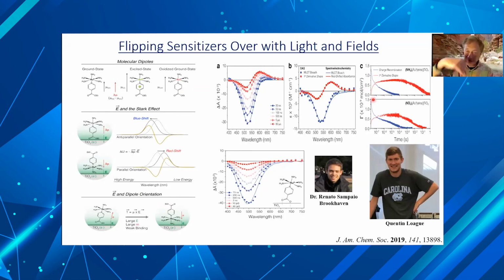Once they recombine, you get a metastable state though, and it takes time for the molecules to flip back down to their thermodynamic state. And that's what this red spectrum is shown. And there's actually a deuterium isotope effect for that. And we're wondering if we use different binding groups here that don't bind too strongly, can we use those as a probe to know when the field shifts over? There are many applications that use electric fields to pull molecules and orient them. But at these dye-sensitized interfaces, it's a new observation.